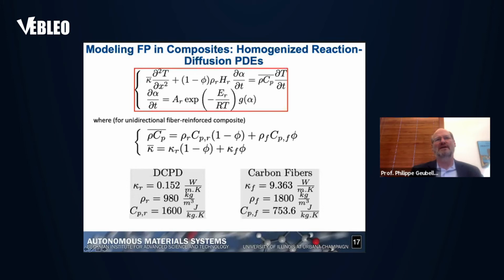So obviously there are many different models to homogenize the thermal properties of composites. For unidirectional composites in the direction of the front, we can simply use a rule of mixture. But there are many more complex ones for different types of configurations and different types of propagation direction. But what I want to emphasize here is the key difference between the thermal conductivity of the resin and the thermal conductivity of carbon fibers. You can see there's almost 2 orders of magnitude difference between the two of them. And we expect that the difference will have a very important effect on the propagation of the front.